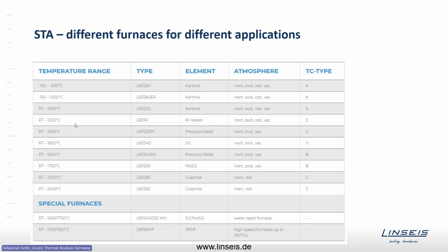There are different possible options. The standard option would be a SiC heated furnace, which is cheap and quite robust, which allows almost any kind of atmosphere. However, if you want faster heating and cooling, we have metal furnaces. We even have infrared furnaces. We have metal furnaces for platinum rhodium heating and even tungsten heating for higher temperature ranges that are quite expensive. However, they have unsurpassed speed regarding heating and cooling rates. So it depends a little bit on budget, availability, temperature range, as well as desired atmosphere, which furnace might be the right one for you.